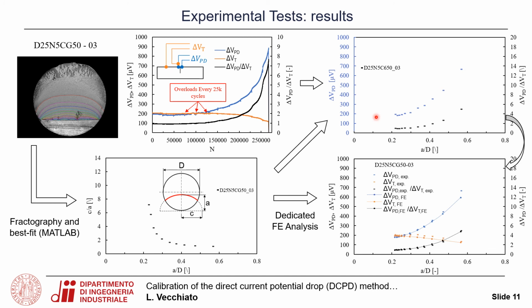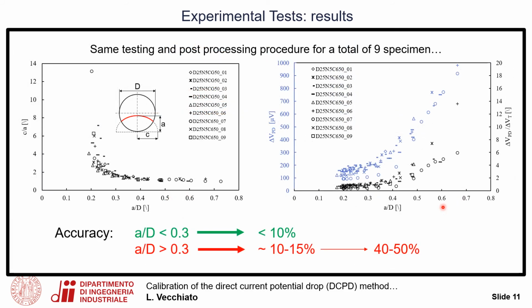Then, by performing dedicated finite element analysis, it was possible to check the differences between the estimated values of the potential drop and the experimental one. Interestingly, the accuracy found on a total of 9 specimens was quite good for small crack size, for a over D smaller than 0.3. The errors were in the order of 10%. For greater crack size, the error was on average about 10 to 15%, but sometimes up to 40 to 50%.